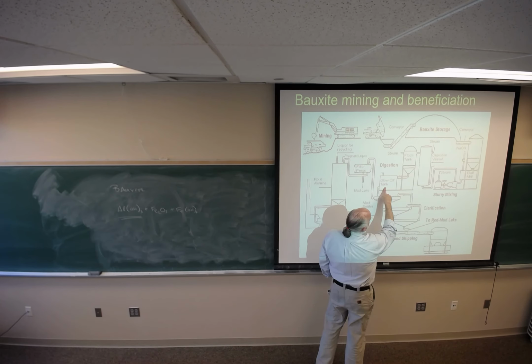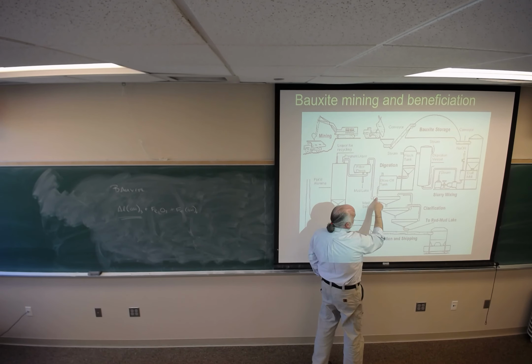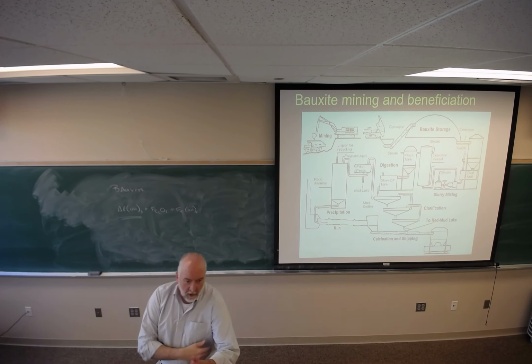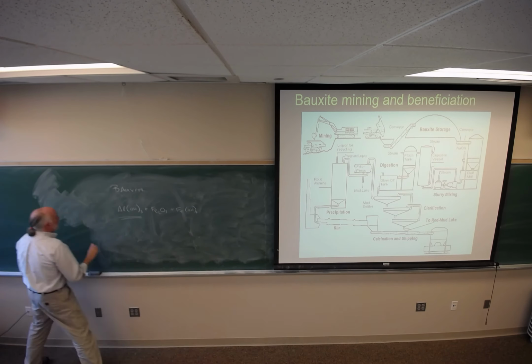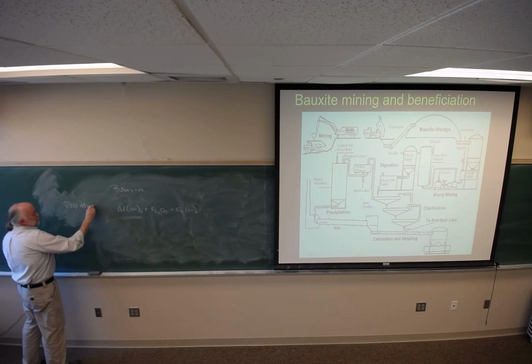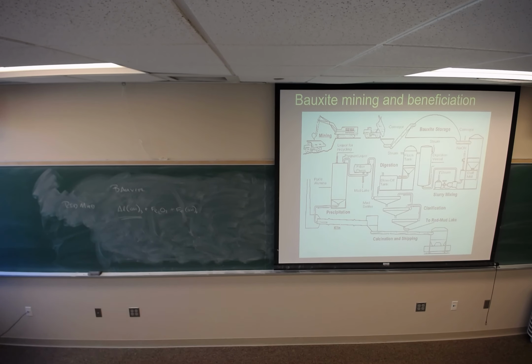Then into a flash tank or blow-off tank. And then this material, the red mud or the slurry that contains iron, is now called red mud. So if you have seen references to red mud, there was a somewhat famous event several years ago, less than 10, I believe. Red mud basically is the byproduct of producing aluminum from bauxite. No one has really found a use for it yet. It's not big enough to justify looking at it as an iron ore source to make iron. There's just not enough of it, even though there's millions of tons of it. It's not enough to justify that compared to iron ore that's being mined. And so the consequence is that this material sits around.